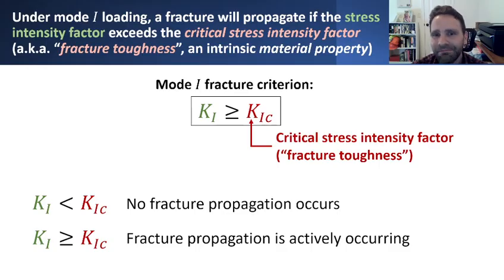So let's try developing a fracture criterion that is expressed in terms of that quantity, the stress intensity factor. And that's precisely what a lot of these classical methods for developing fracture criteria did, and it largely applies and is a pretty good predictor for mostly brittle materials and brittle fracture. In those cases, you can apply this sort of stress intensity factor based failure criterion to assess when fracture will occur by constructing a relatively simple inequality like the one shown here. We define that fracture will occur when the stress intensity factor exceeds some critical value.